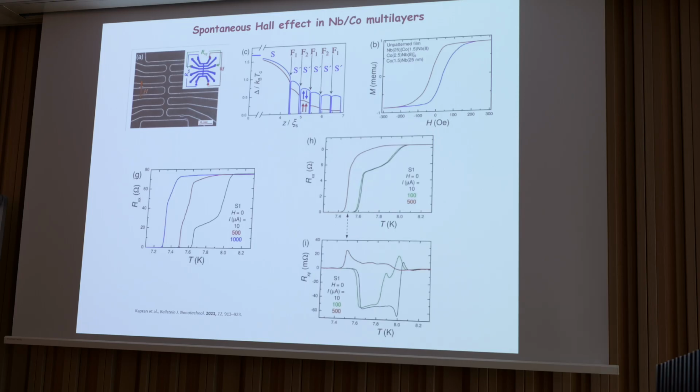And it is interesting to see the correlation with the Hall effect. Now, this is a simultaneously measured longitudinal transport and the Hall coefficient at zero magnetic field. I emphasize this. So this is a spontaneous Hall effect that we see. It's a huge Hall effect, which is induced by flux flow. So the flux flow Hall effect is tremendous. Above TC, there should be some Hall effect due to the presence of the ferromagnet. In fact, if you have a microscope, you would see it, but it's tiny on this scale. So it's totally dominated by flux flow.